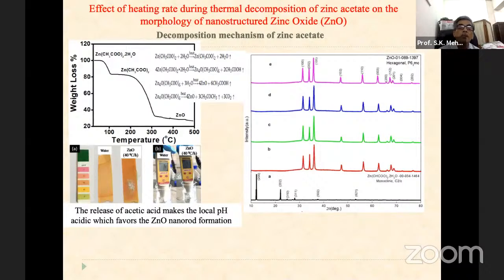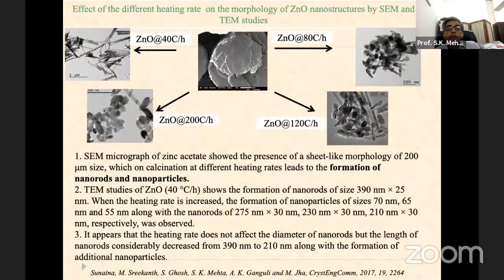So we tried to see how the release of acetic acid makes the local pH acidic, and we wanted to find out the reason. So we found that it favors the zinc oxide nanorod formation. Once release of acetic acid makes the local pH acidic, it favors the zinc oxide nanorod formation. That's why nanorod is formed. So this is XRD. You can again compare one with another and find out how different they are from one another.